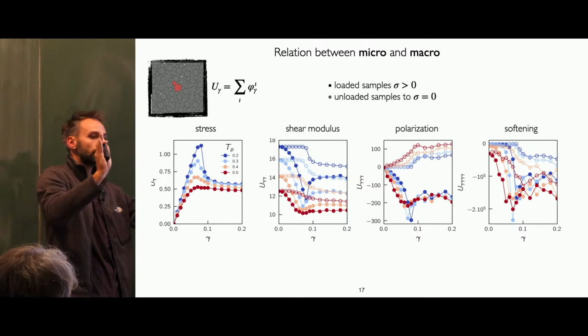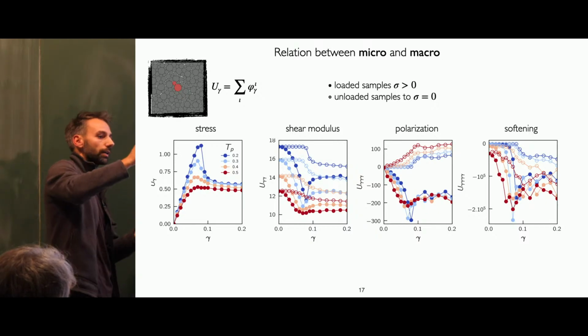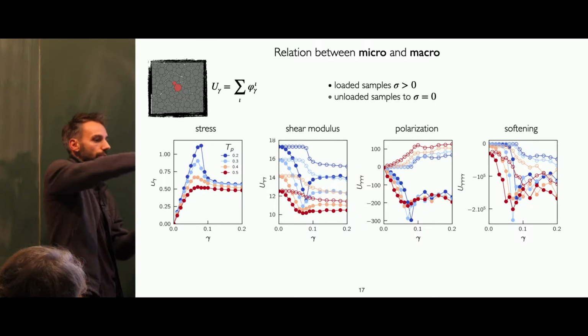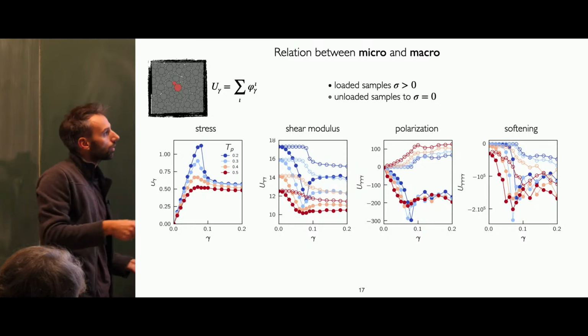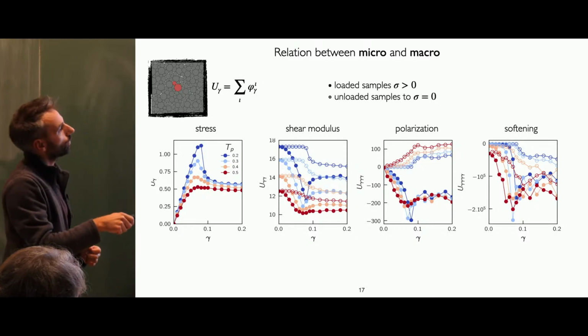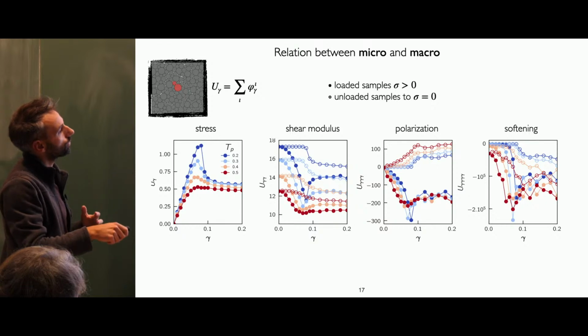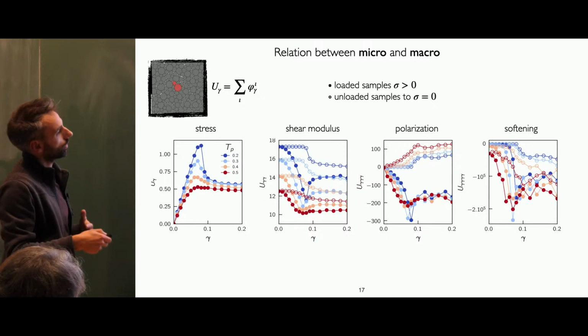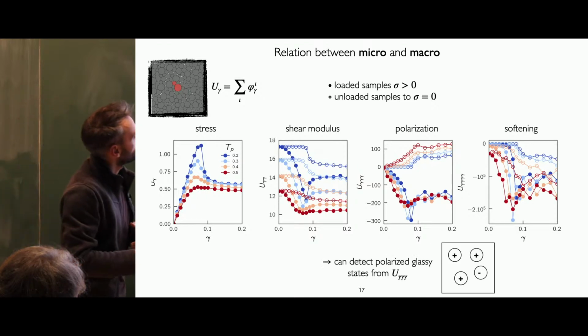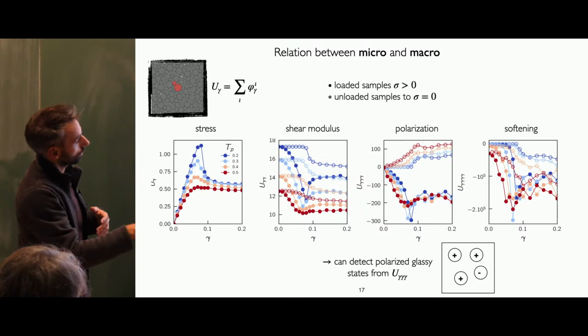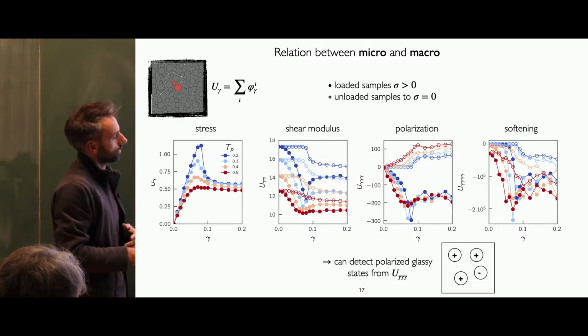Which means that if you take this sample at 0 stress and shear it back, it will fail more in the positive direction than in the negative direction. So, for example, at the macro level, those tools allow you to distinguish between a state that experienced some plasticity or not. Now at the level of the micro, because we can detect polarized glassy states in some sense.